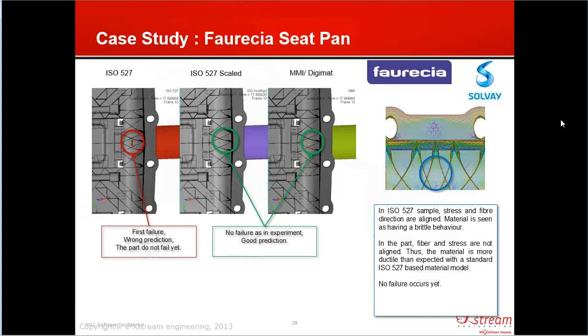So in the first scenario, your loading has really just started to happen, just before we have that stiffness reduction. In the first case with the ISO 527, your very stiff isotropic material model, you have a failure that happens too early and in the wrong place in the wrong direction. For the scaled approach, you don't have that failure, and in the Digimat scenario, you don't have that failure.